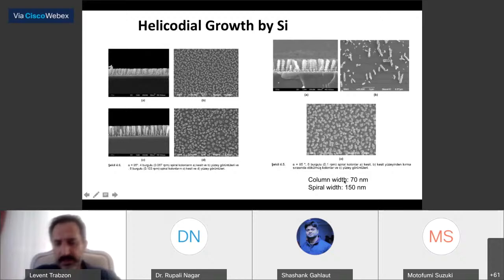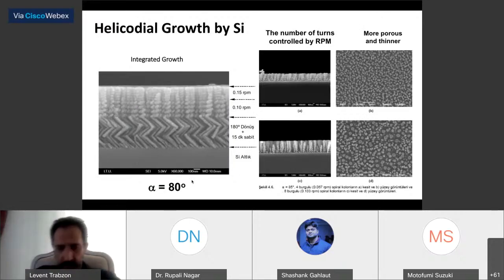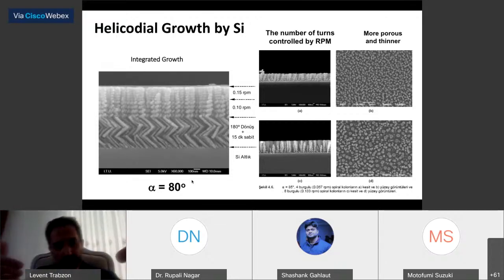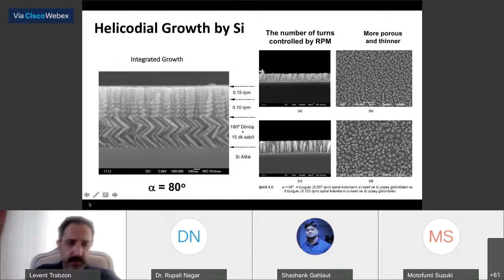The columnar width in our case is in the range of 70 nanometers and the spiral width in the range of 150 nanometers. In our case, the film thickness is around 1 micrometer, and as you see on the right-hand side, the porosity can be easily modified by film growth parameters. You can also play with how you manipulate the substrate, and you can get integrated growth. In this case, this is a silicon material. Again, the incident vapor angle is around 80 degrees here, and you can get a zigzag structure. You can get a helicoidal structure with different properties, so this is nothing but engineering of the nanostructure at the nanoscale.